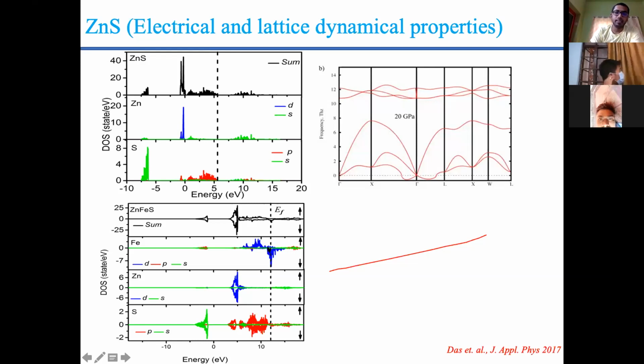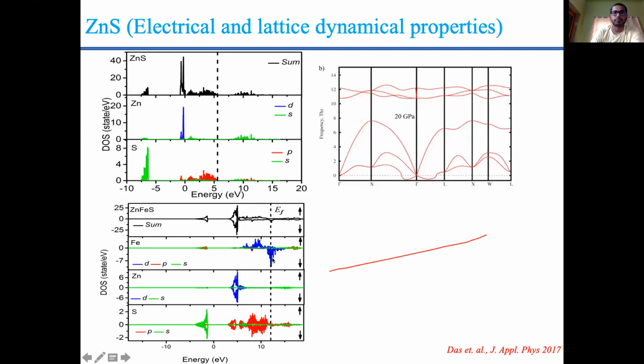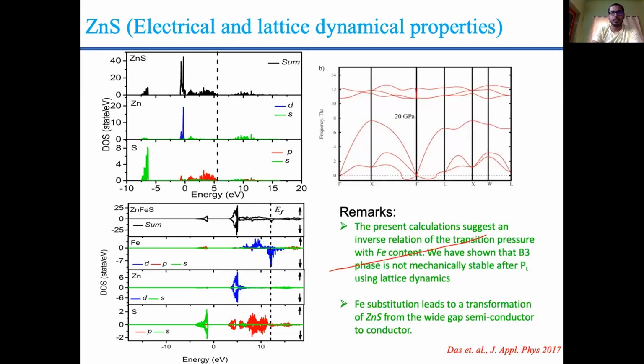Here you can see a finite but unequal number of states even at the Fermi level. So this indicates that the structure turns into a conductor, but with some magnetic moment. To conclude this study, we can say the transition metal impurity has an inverse relation with the phase transition, and this impurity can lead the semiconductor ZnS to become a conductor.